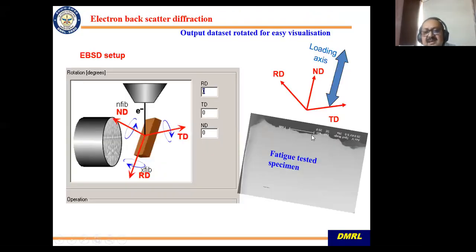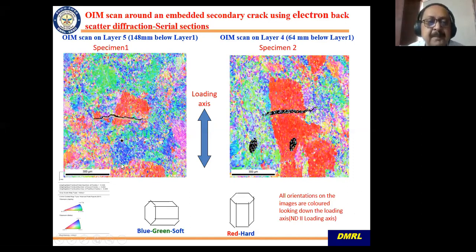Now, this is the broken flat sample that I had shown the micro radiograph of earlier, and this was oriented properly. You note in texture, you have to track the orientation of the sample, and this is the camera, and this is the electron gun, and it was oriented properly. That is, the loading axis is in this ND direction, and then the scans were taken after polishing inside where the crack is exposed.